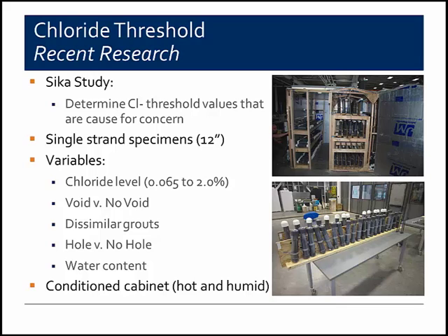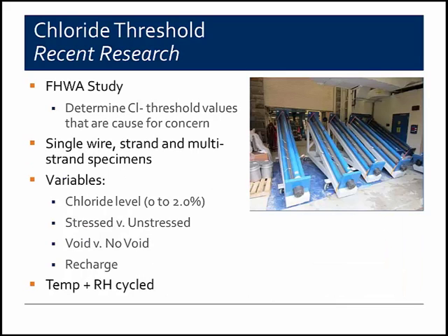Federal Highway is also doing research on the chloride content threshold, and their program is a little more ambitious, both in terms of the variables they're considering and in the scope, but their goal is the same: determine the chloride threshold values that are cause for concern with respect to corrosion. They evaluated single wire specimens, single king wires, single strands, much like Sika's work, and then multi-strand specimens in somewhat of a mock-up assembly that is shown in the photograph on the right.